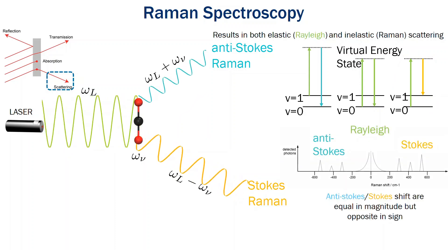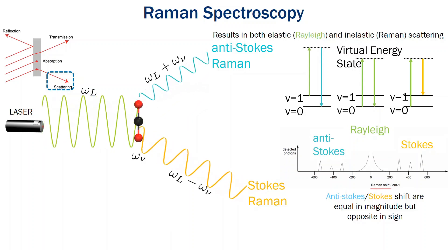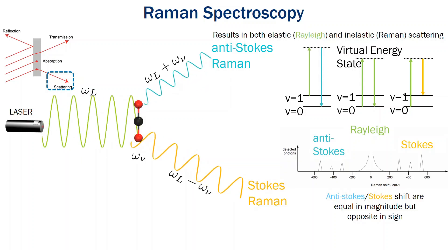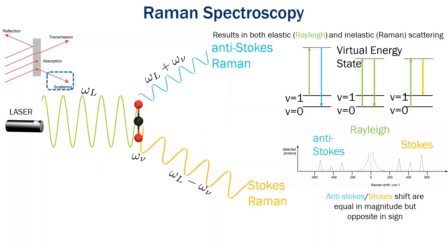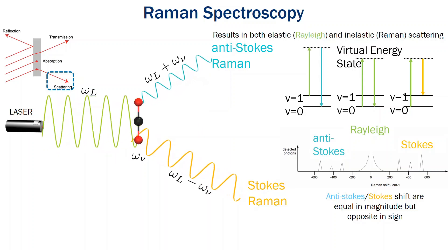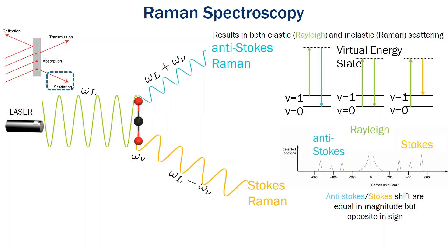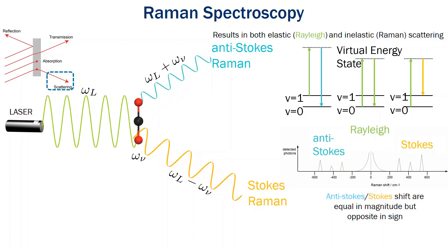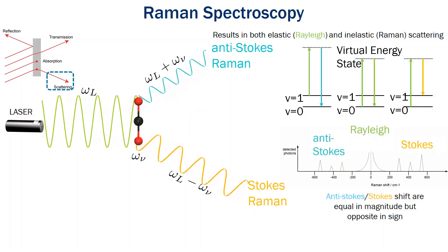Shown here is a generic Raman cartoon spectrum where we see that the x-axis is in units of Raman shift, which is really a shorthand for relative wave number change, and it's relative to whatever wavelength laser that we're using. So that value at zero is the elastic scattered line, and it will always be zero regardless of what wavelength laser we're using because it's relative to that source. The Raman shifts correspond to the energy delta that we see in the Jablonski energy diagram above.